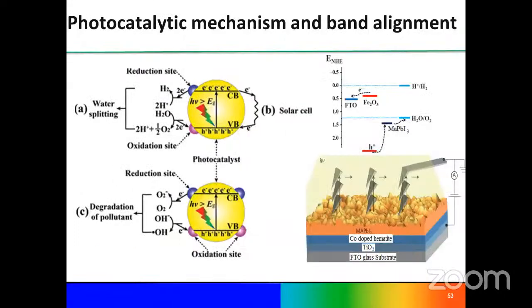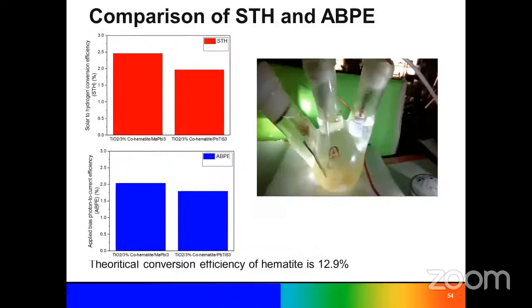So in this diagram, the theoretical solar to hydrogen conversion and photon absorption ratio for the cobalt doped hematite with methylammonium should reach around 12.9%, but still we are struggling, where we reach around 2.5% efficiency. So some of the parameters we still need to optimize to reach the theoretical value.